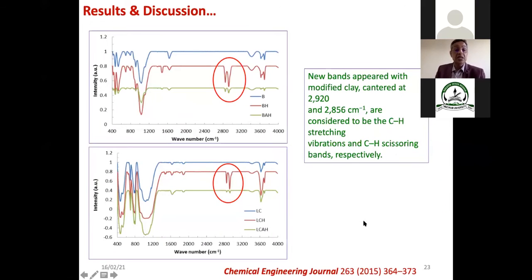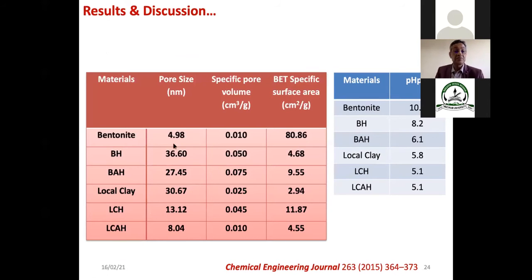So anyway, this is the IR data that we got. You can see the additional peaks in the modified materials. The peaks centered around 2,920 and 2,856 centimeter inverse are considered to be the CH stretching vibrations and CH scissoring bands. That confirms that the organic molecule has been successfully introduced into the clay materials. Our intention was to check whether it was successfully introduced or not, and that was confirmed by the XRD and IR data also.